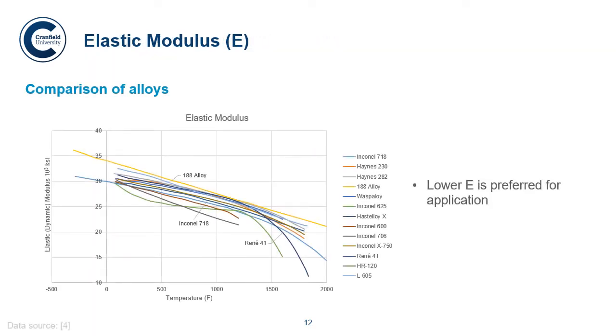So we also looked at the elastic modulus of the alloys. A lower elastic modulus is preferred, but not too low, or we're going to get more brittle type fractures. So we're looking more for a mid-range point in this category. We've got Inconel 718, which is the more middle ground, followed by Rene 41, which is mid to high as you come through the range, and then starts to really dip off in its elastic modulus as it gets to very high temperatures. And then you've got alloy 188, which again is a very straight line throughout.